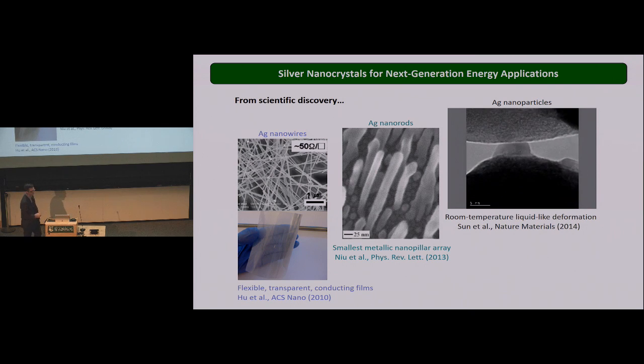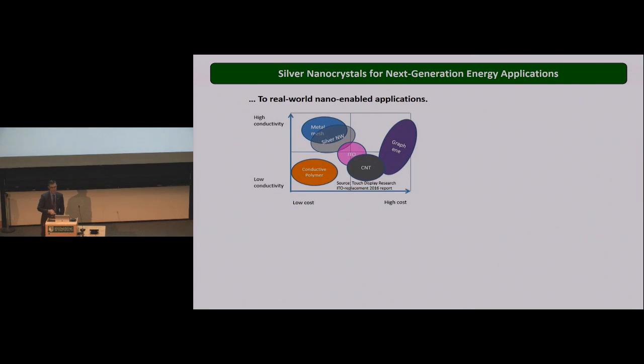So this is very, very new here. So now, real-world application here. So silver nanowires, when they are represented on a chart, this represents the electrical conductivity of the material versus the cost for producing the material. The current technology relies mostly on the transparent electrode indium tin oxide, the ITO, okay? And we see actually those silver nanowire networks perform better and at a lower cost. So that's attractive. But there's more to this.